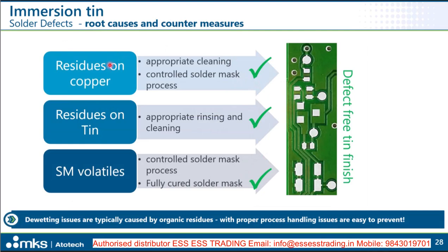And this brings me to a brief summary on what can cause soldering defects in immersion tin. In very many of the cases, they can be traced back to contaminations, either residues on copper which are not properly removed before the immersion tin process, which can be even residues from the solder mask process. For example, if there was not a fresh developer anymore, then there is organic remaining on the copper, which may not be properly removed in the pre-treatment process.